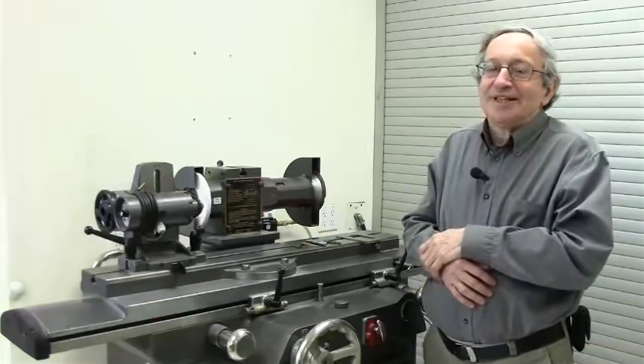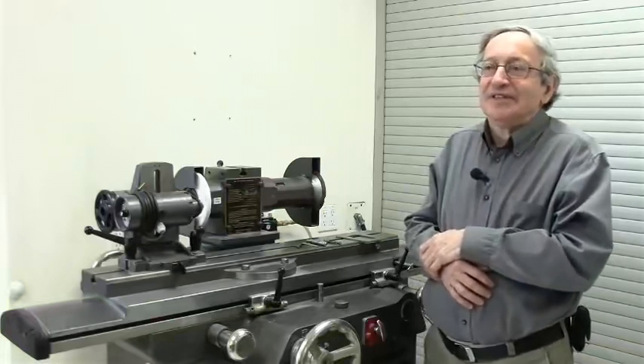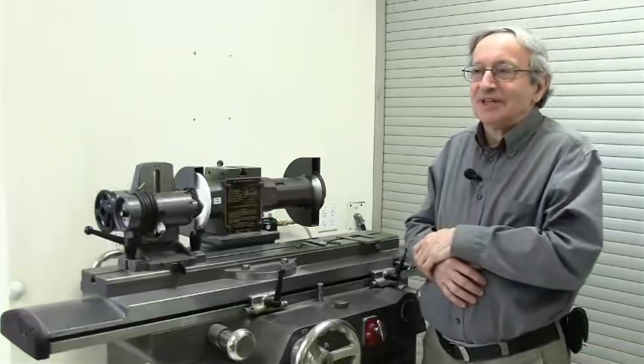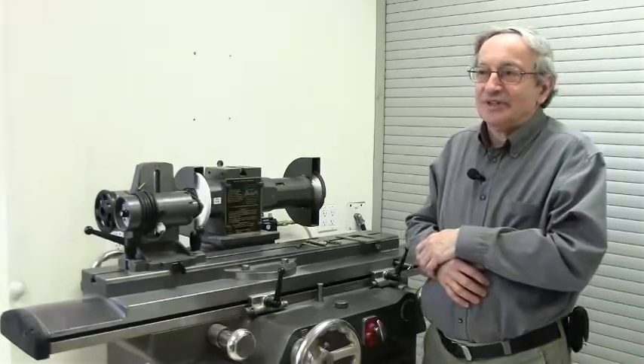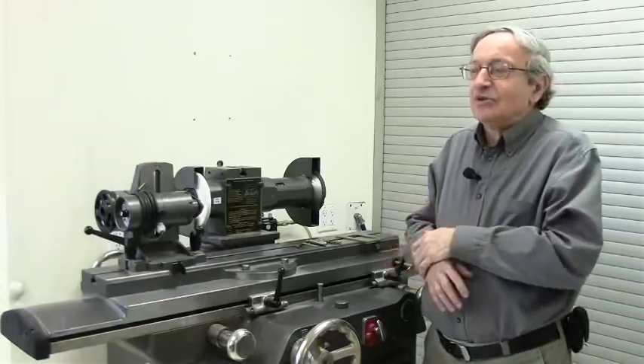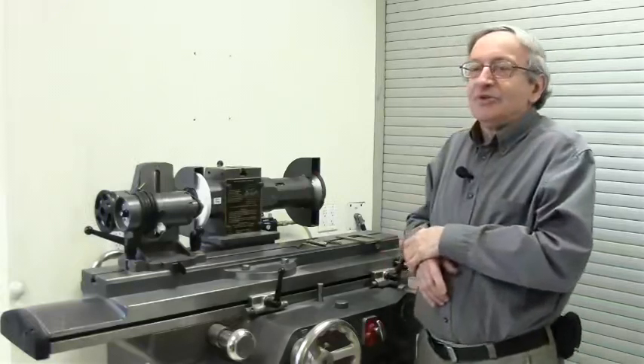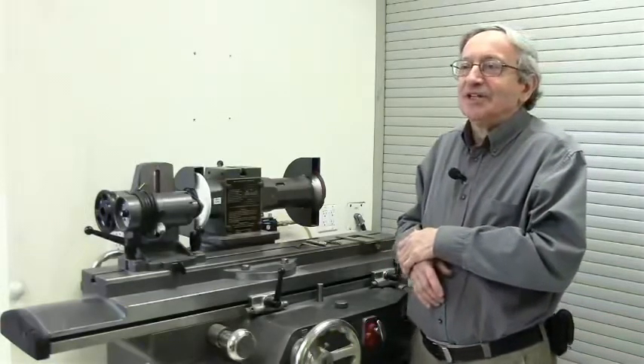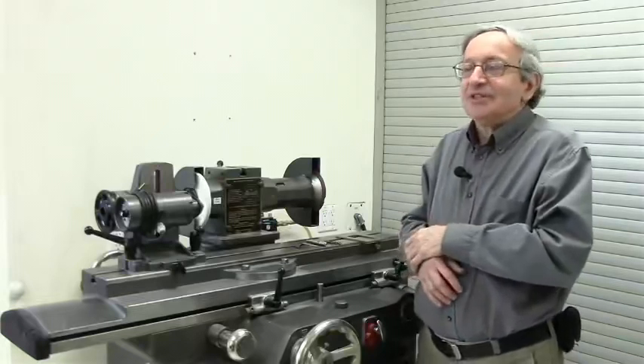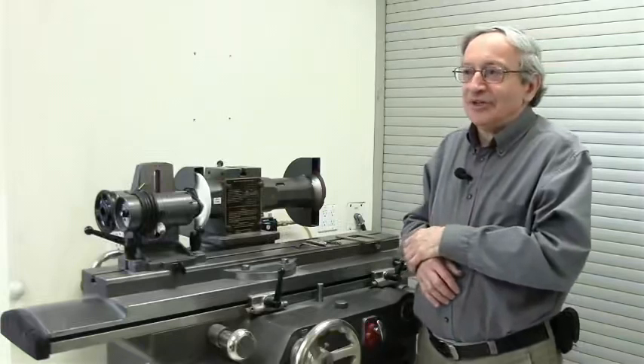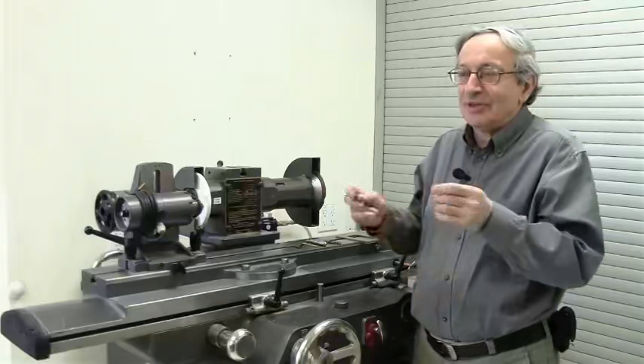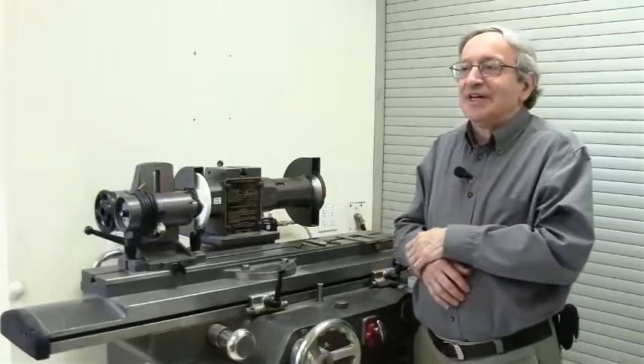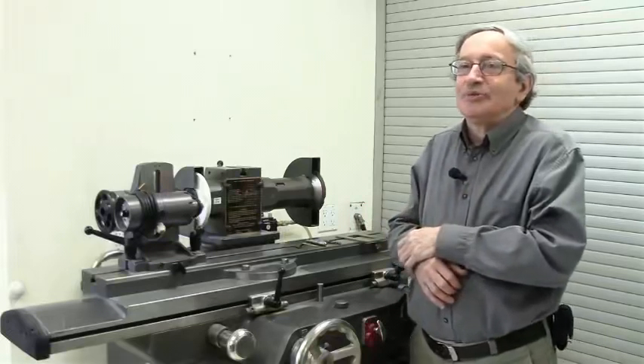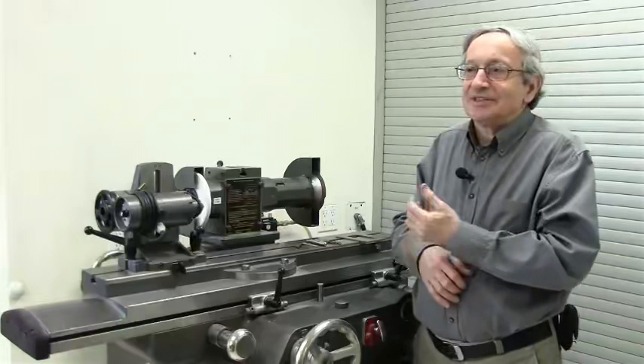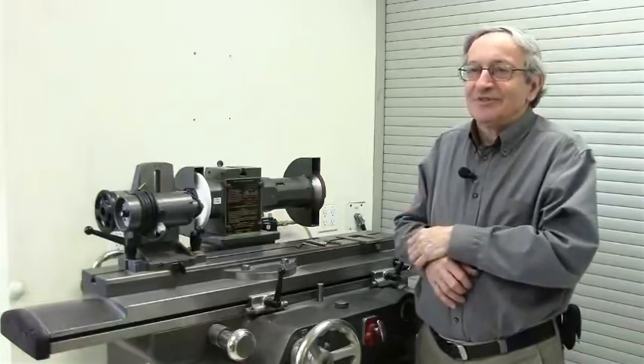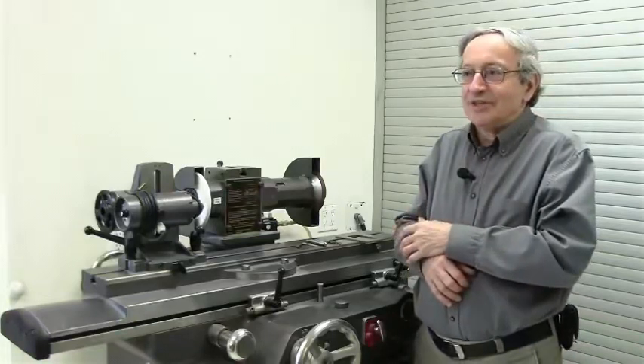Now, sometimes you have to grind it anyway because the very outer layer of steel decarburizes when you heat it up, so it loses hardness unless you have an inert atmosphere oven. So, as a good compromise, use A2 steel. When you harden it in an oven, you can wrap it in stainless foil to prevent decarburizing. The best thing is you wrap it in paper first and then in stainless foil, and you seal the stainless foil bag, or spot weld it or seal it. So the little air which is inside, the oxygen will be absorbed when the paper carbonizes, and this happens before the steel loses carbon. So if you wrap it in paper, the surface would not decarburize.